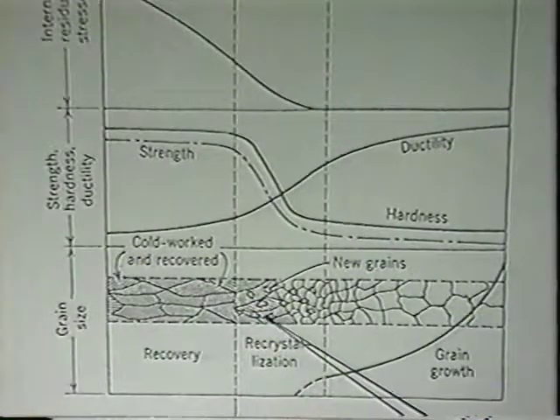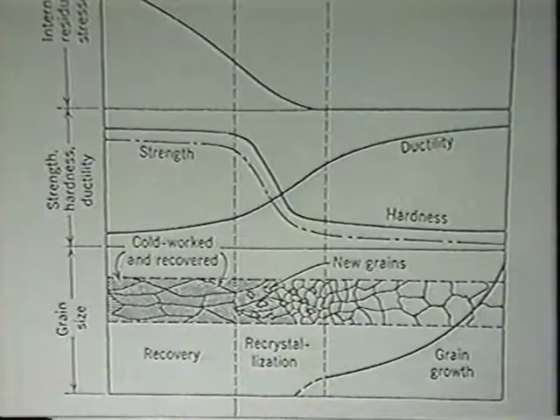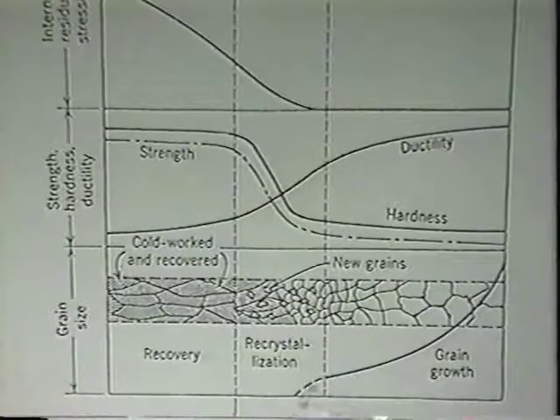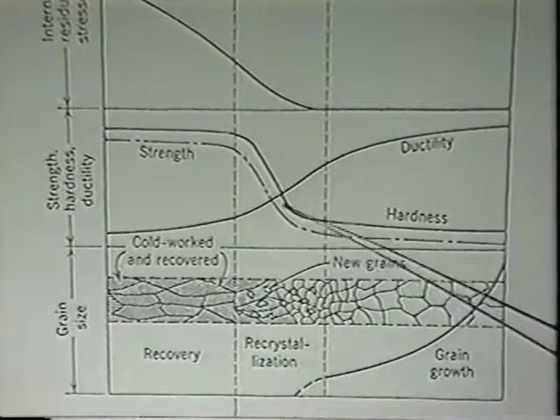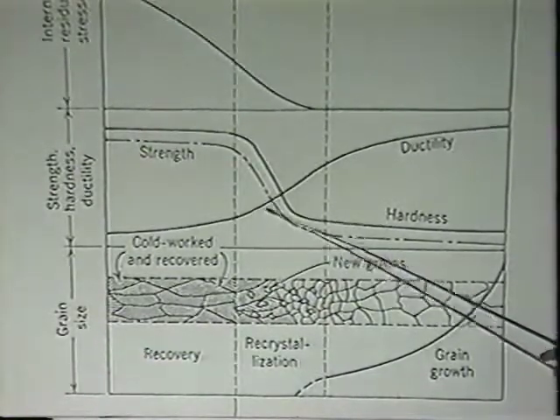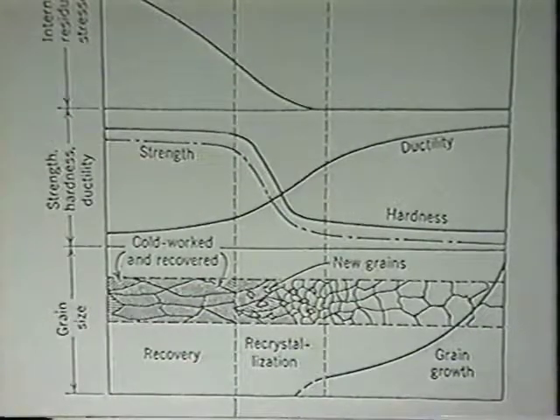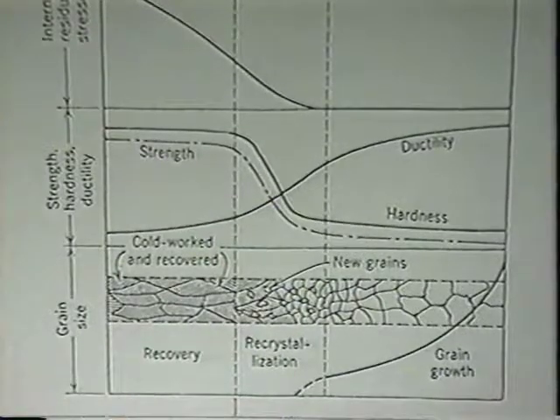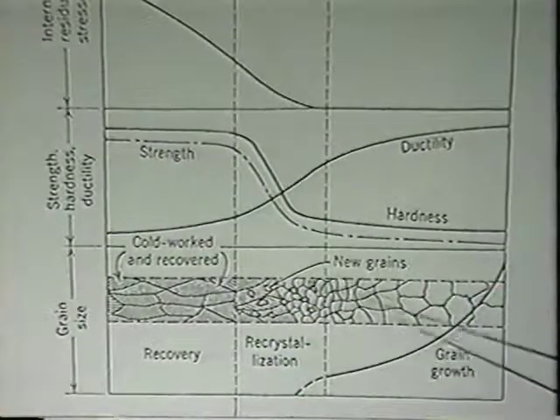As we climb the temperature range, these elongated grains are going to recrystallize, where they go from elongated grains to, it's like a rebirth. They go back to an equiaxed round grain. This is the first stage of creating drawing quality steels. Notice that in the schematic of ductility and strength, through this process you have a dramatic increase in formability or stretchability, but also the strength rapidly decreases. If you were going to buy a commercial quality steel, we anneal it just to recrystallize it. That's it. We get it to this stage right here, recrystallized.